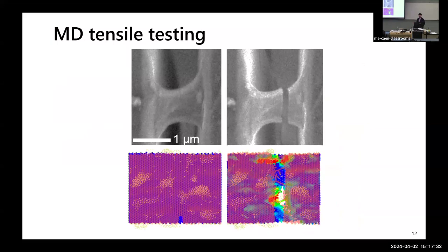So what we're doing here, you can see that process playing out. You're seeing two layers in this multi-layer stack. The first layer is the layer that's pre-cracked with the functional groups just hidden, and it's translucent. What you're seeing beyond that is the second layer, which has a color mapping associated with local strain. And lo and behold, what we see when we advance this crack through the system is we get another crack nucleating directly spatially located below, in the layer below or the layer above, as the case may be, from that initial crack that propagated across.